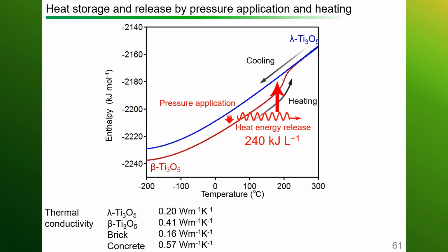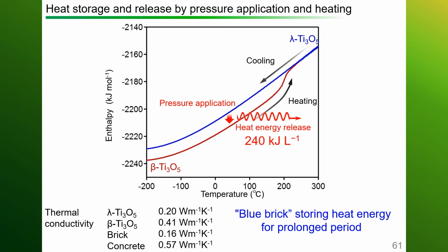But even if the phase goes back, it keeps the latent heat, and the heat will only be expelled by pressure when it's pushed. And this is why the blue bricks can store heat energy for a long time. As I said at the beginning, this material solves the time gap issue and has been attracting attention. Let's take a look at the mechanism.